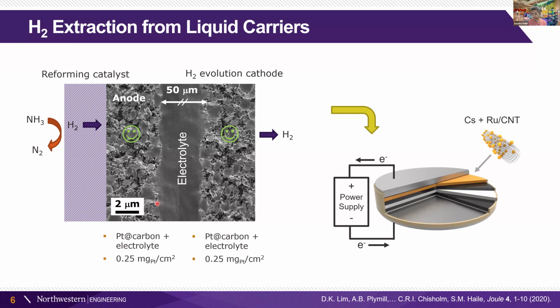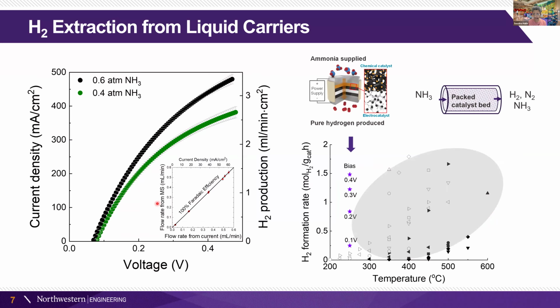And the way that we put this together, we needed a reforming catalyst. The one that we used was one that was already reported in literature. We synthesized it ourselves, which is ruthenium on carbon nanotubes with additional cesium, which seems to change the electron density on the ruthenium and enhance its activity for the ammonia decomposition. We put that together, and we then create a cell where we are supplying ammonia and extracting the pure hydrogen out of it.